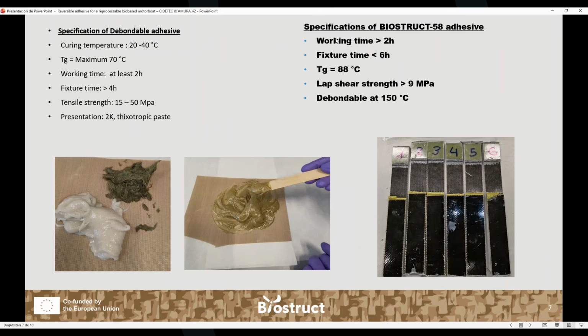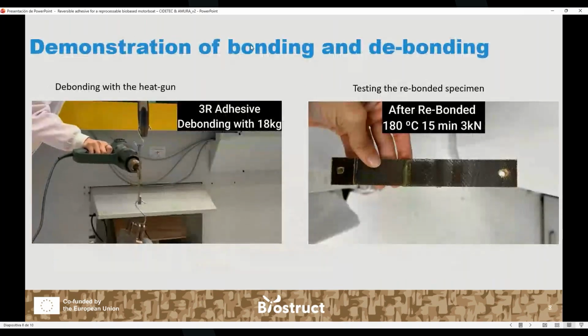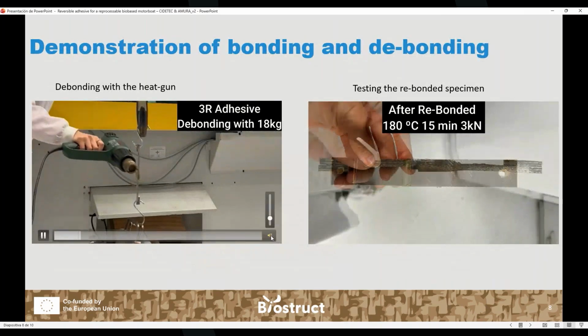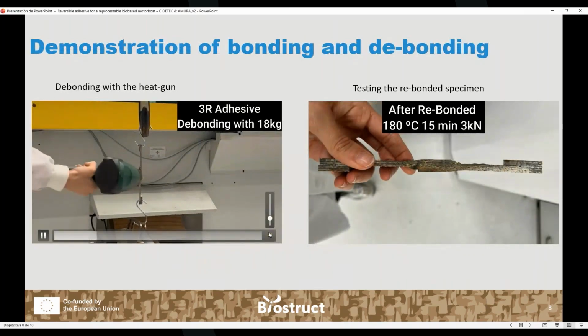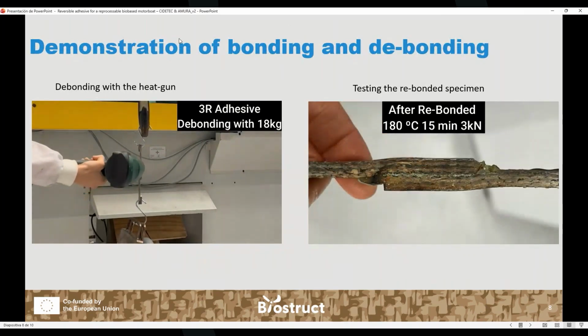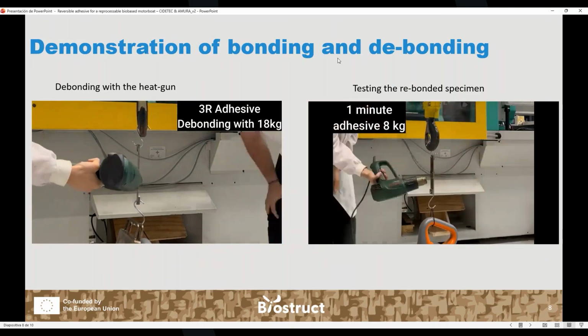And here you can see the values that we obtained: an adhesive that has a working time higher than 2 hours. The fixture time is around 6 hours. We have a TG of 88 degrees, a lap shear strength of around 9 megapascals, and an adhesive that is debondable at 150 degrees. And here, you can see two videos where we demonstrate this debonding and rebonding capacity.